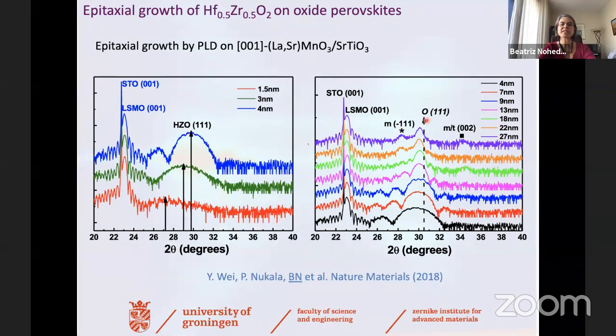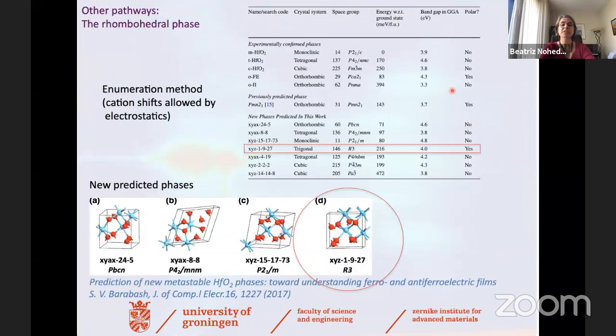But it's also interesting that the diffraction peaks that we obtained were not exactly those expected for the orthorhombic phase. And we actually figured out that this was not an orthorhombic phase, it was actually a rhombohedral phase. So this is still a new phase, and this rhombohedral phase had actually been predicted by calculations before, that it is higher in energy than the orthorhombic phase and still is accessible when the material is under high strain.